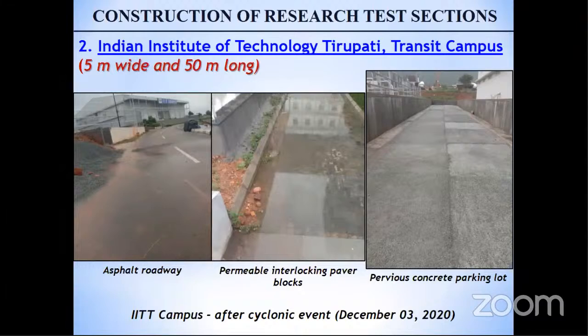But on the right side, you see there is a pervious concrete parking lot. The entire campus, I tell you, was filled with water all across. But this was the only stretch where not a single drop of water actually accumulated over the surface. The entire water was drained into the underlying layers.